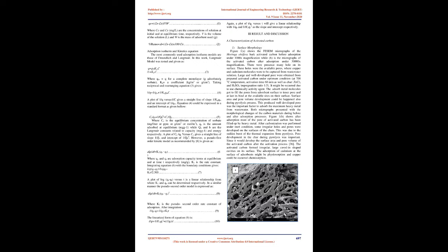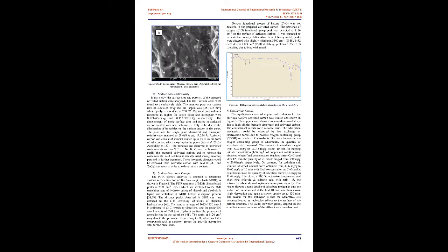The precursor was placed in the furnace at 700 degrees Celsius with a heating rate of 10 degrees C/min for 60 minutes. During the carbonization process, purified nitrogen was flowed. It was cooled at normal temperature. These activated carbon samples were washed several times with distilled water. The washed samples were dried in the oven at 110 degrees Celsius for 15 hours. These were then sieved with a 400 µm sieve. The activated carbon samples were kept in a polypropylene bottle to avoid moisture. These prepared activated carbons of Moringa oleifera bark were used for the experiments as the adsorbent in the adsorption process.